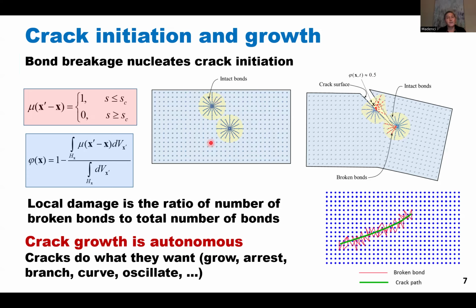If you break it, then it no longer carries any force, right? So you nucleate the crack, and the fact that you have only one bond broken doesn't mean that you're going to have a crack. So you have to have a way of measuring the local damage, and this is the way we measure it. So you look at the total number of bonds at the beginning, and then you look at the number of broken bonds. So in this particular case, as you can see here, this point X lost 50% of its bonds. So the ratio is about 0.5, number of broken bonds to the total number of bonds. Then we say you create a crack surface.